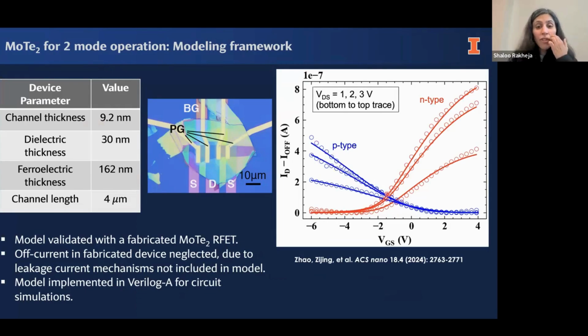I should mention that when we fabricated these devices, there was a lot of leakage in the devices, and we could not really figure out why that massive leakage was happening. So in our model, we've only been able to calibrate the current minus the off current. So we're just assuming that the off current is 0 for these devices.